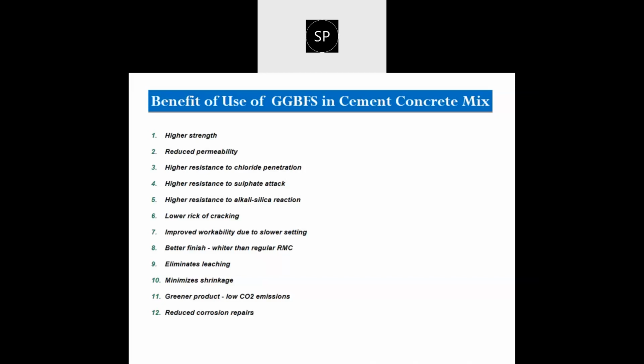This is one of the major benefits of using PSC cement. It has a lower risk of cracking, improved workability due to slower setting, and a better finish, whiter than the regular RMC. In terms of color, the GGBFS is basically milky white, while the conventional OPC is slaty in color. So in comparison to the conventional cement concrete mix, the concrete made with GGBFS will be comparatively white, and therefore it gives you a better finish and appearance. It eliminates the leaching possibility. Since this is primarily an alkaline material, the combination of GGBFS and cement reduces the possibility of leaching.